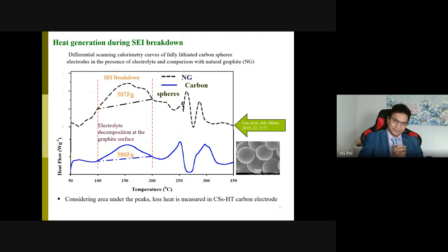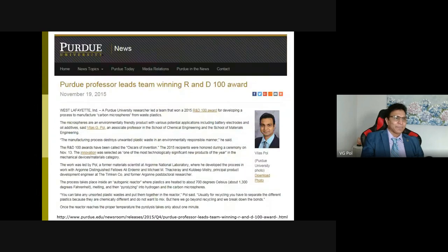For example, you make the battery and we start heating the battery at higher temperature. We would like to have the thermal runaway of the battery. As you heat from room temperature to higher temperature, as you can see, our material only generates 380 joules per gram exothermic heat. That is a differential scanning calorimetry. On the contrary, much higher heat is generated with those potato-shaped particles that we can buy from the market. So there are advantages to making the battery electrode material spherical in shape.